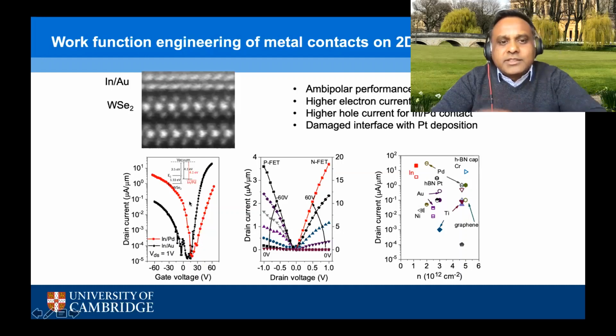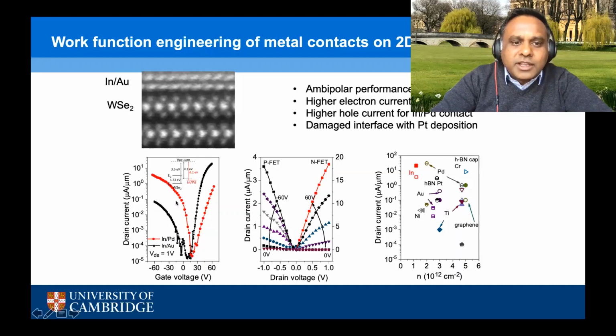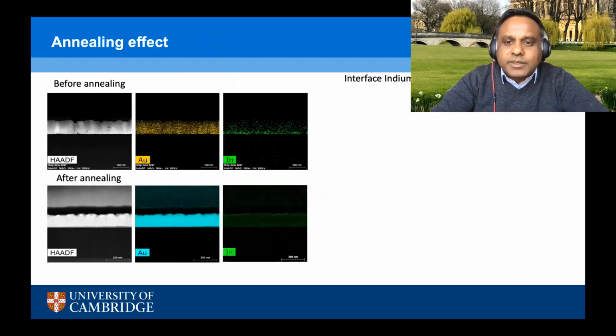So this suggests that there is some influence of work function engineering in terms of injection of holes with a higher work function metal relative to say indium gold. And then we get nice output characteristics on both the p-type and the n-type. So we're able to at least make ambipolar types of devices with indium alloyed contacts.